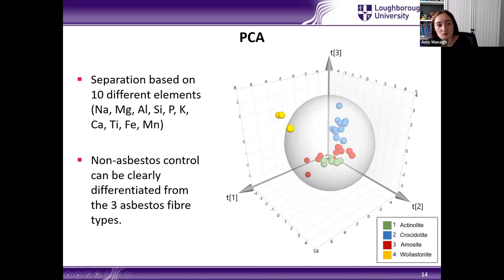And you can see in this three-dimensional PCA data that our wollastonite fibers shown in yellow are actually very well separated from the other fiber types there, from our three asbestos fibres. So we're very clearly able to distinguish our asbestos fibres from the control sample.